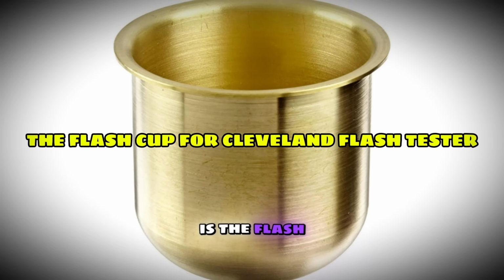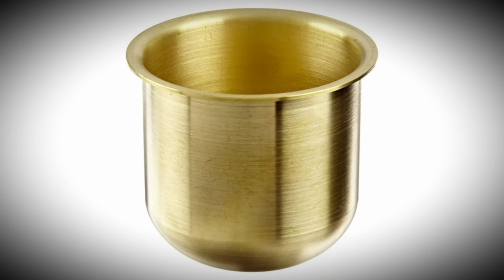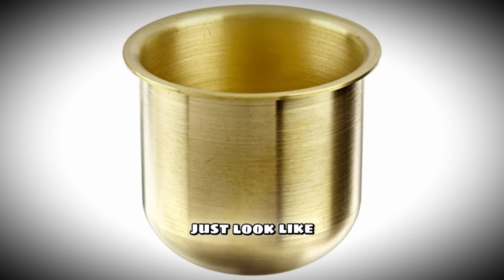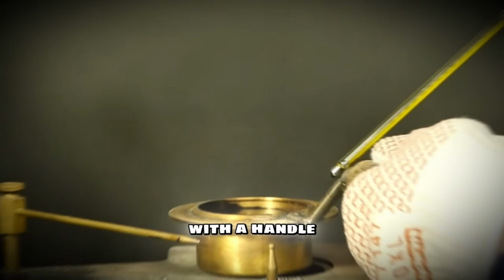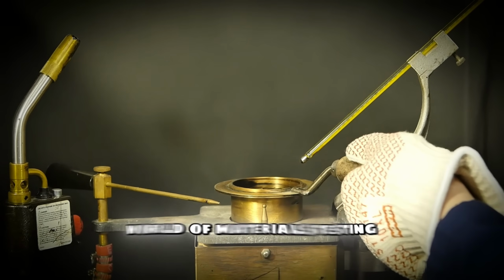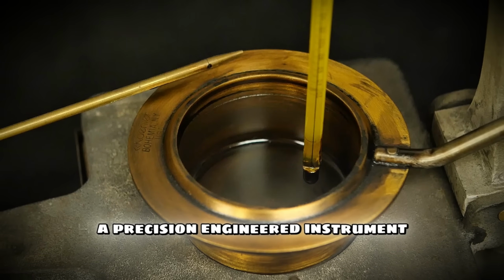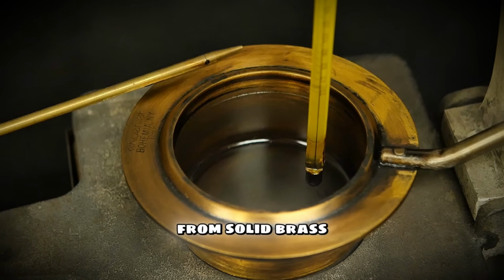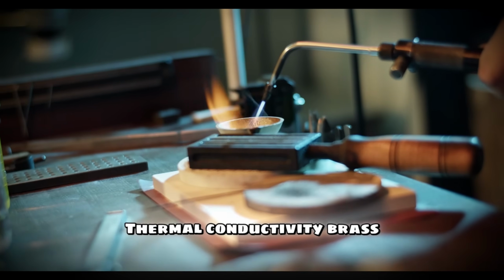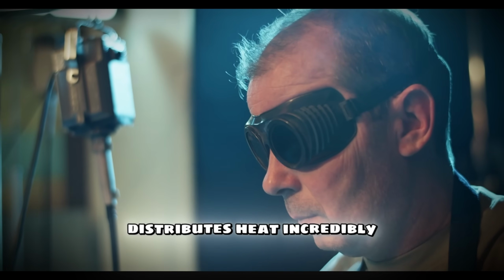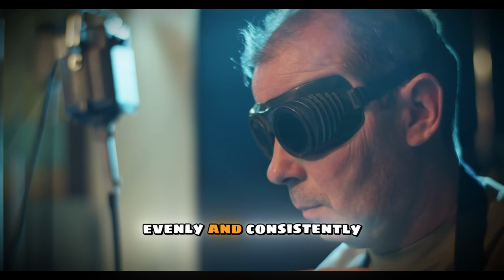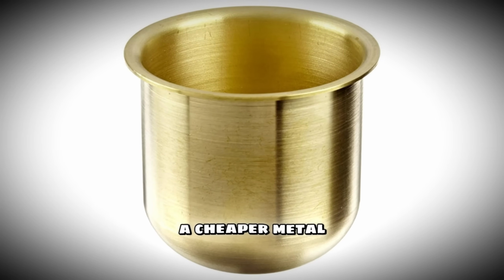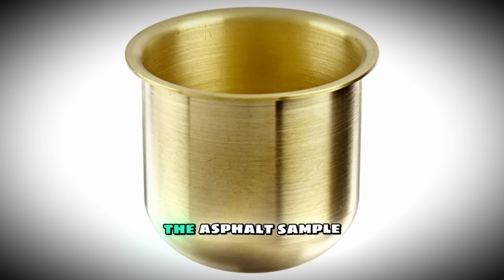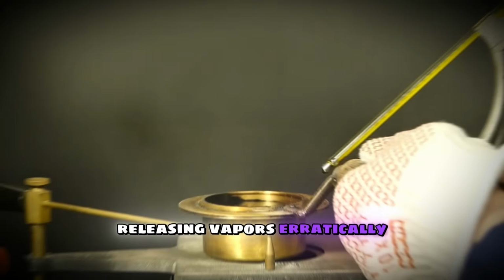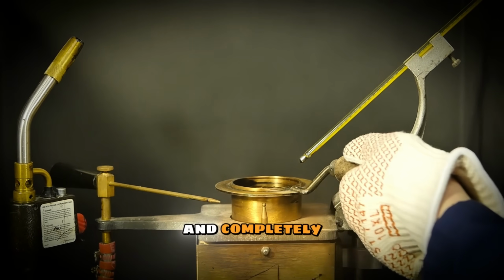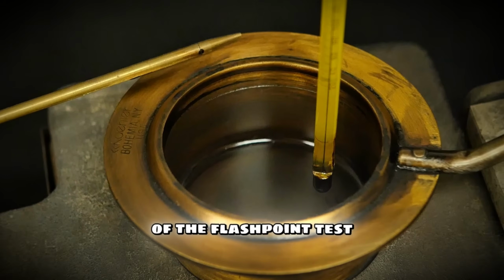Up first is the flash cup for the Cleveland flash tester. To the untrained eye, this might just look like a heavy little brass bowl with a handle. But in the world of materials testing, this cup is a precision-engineered instrument. It is forged from solid brass for a very specific reason: thermal conductivity. Brass distributes heat incredibly evenly and consistently. If the cup were made of a cheaper metal that developed hot spots, the asphalt sample would heat unevenly, releasing vapors erratically and completely ruining the accuracy of the flashpoint test.